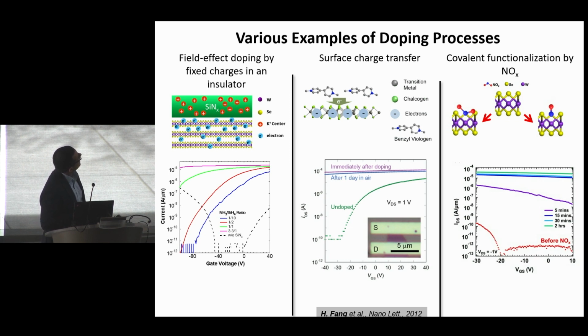Another approach to do remote doping is to use surface charge transfer. In the case of surface charge transfer, you use species, whether it's thin films of materials like oxides, or molecules, or even atoms that are either electron withdrawing or electron donating. Basically, materials that have very different work functions compared to your semiconductor. If you have a very different work function, there will be charge transfer. When that happens, you will have charge separation. You will have basically fixed charges on top, and the semiconductor will then be effectively doped.